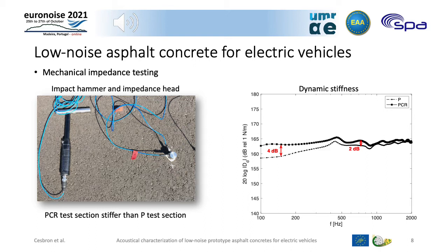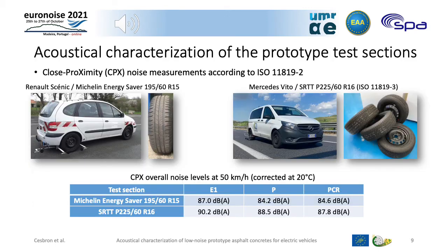Also comprising crumb rubber, it is observed that test section PCR is stiffer than test section P, with a difference up to 4 dB below 400 Hz and about 2 dB above 400 Hz. Let's turn to the acoustical characterization of the prototype test sections.